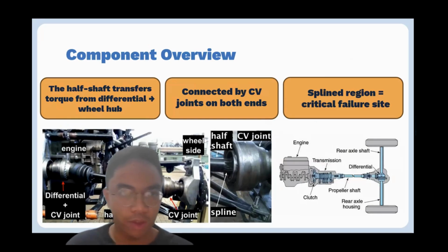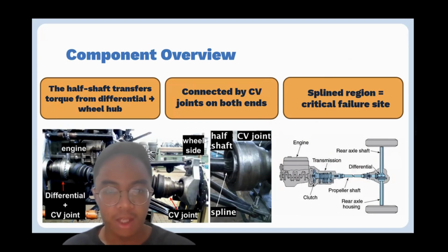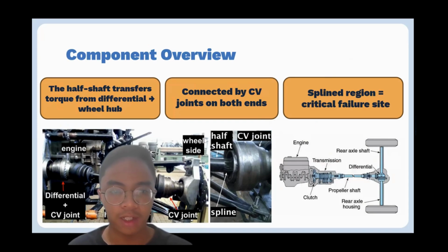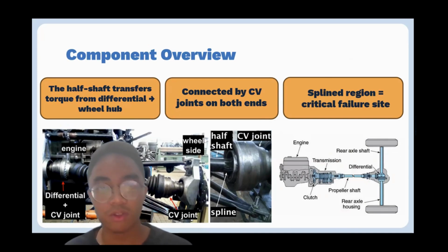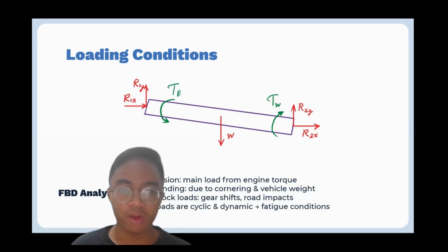So the failed component, as you can see, in this case was the transmission half shaft. Its role is to transfer torque from the differential to the wheel hub, allowing power from the engine to reach the ground. At both ends, constant velocity or CV joints allow for smooth angular motion. The shaft itself has splines cut at both ends, and these splines are where torque is actually transmitted. The critical location, and ultimately where the fracture occurred, was at the spline root, a geometric transition that naturally creates high stress concentration.